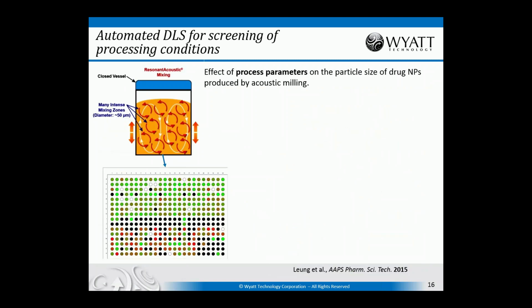Another way to utilize the dynamic light scattering capabilities in the microwell plates is to identify optimal processing conditions for nanoparticle formation. This publication, contributed by Leung in AAPS PharmSciTech, described a process of optimizing milling conditions for creation of drug nanoparticles. Their drug was a small molecule in solid form, and they were milling it using this acoustic process, which involves putting in some small particles, applying acoustic energy, causing those solids to break up, and in solution there are also some polymers which coat the particles and prevent their aggregation.